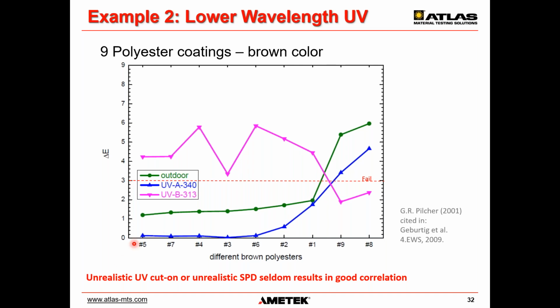Note that this is not a time series. It's not 1, 2, 3, 4, 5 hours. It's not a time curve. These are the different samples. Sample number 5, 7, 4, 3, 6, 2, 1, 9, 8 of these brown polyester coatings, different polyester coatings with brown color. And they are in order of stability. Moving from left to right, the coatings are in decreasing performance. So these are the best and these are the worst, because this is the pass-fail line here. Delta E, pass-fail line, and you see these samples are in order of their performance.